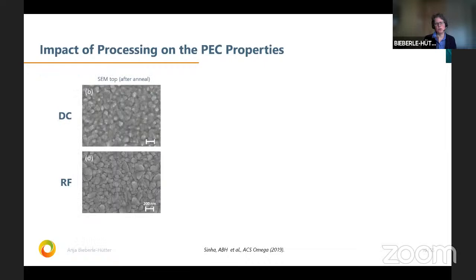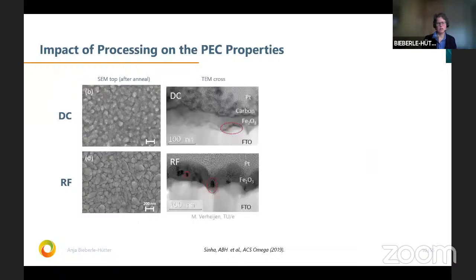When we now look with the SEM on the top of the samples, we see that from the top they look rather similar, the DC and the RF samples. When we do a TEM cross-section with FIB cutting, we see here the FTO layer, and the hematite thin film on top. In the DC case, we sometimes have some holes at the interface, and in the RF, we see some holes in the layer. So this could be an indication why we get different performance.